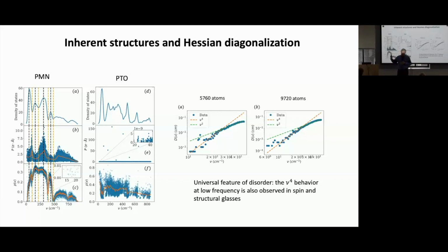Instead, if we use the model without this effect, we get an exponential decay, which is wrong. However, the difference between the two in that case is not so large, because it is dominated by the clustering of these dipoles at shorter range, and the difference is actually smaller than the error of the DFT in the dielectric constant itself.